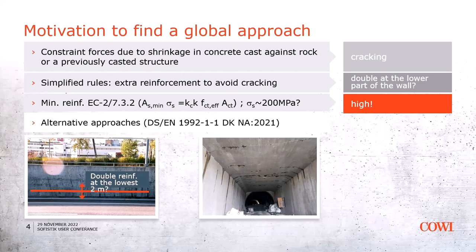The Eurocode also covers this effect using the formula in chapter 7. The formula is based on balancing the cracking force of the concrete with the stresses of the reinforcement, and putting as a limit a stress level in the reinforcement that gives control of the crack width. Usually to achieve this we would need to balance with around 200 MPa of stress in the reinforcement — depending on the diameter and spacing of the bars — but this gives very high reinforcement.